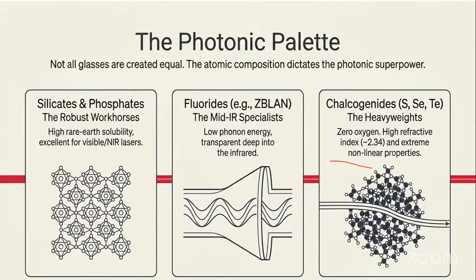When I deal with fluorides, I can tune it in the mid infrared region because of its low phonon energy. They are transparent in the infrared region as well as the visible region. If I look at chalcogenides, they have a high refractive index, and because of this they exhibit non-linear optical properties.